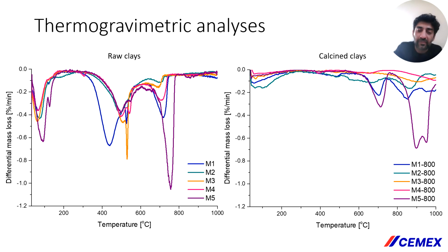Okay, so these are the differential mass loss curves of both the raw clays and calcined clays. Immediately you can spot that the characteristic dehydroxylation mass loss between 400 and 600 degrees Celsius, which was present in the raw clays, was not observed in the calcined clays, which is concurrent with the dehydroxylation of kaolinite.